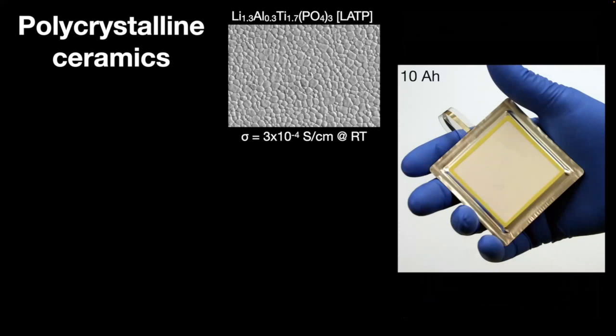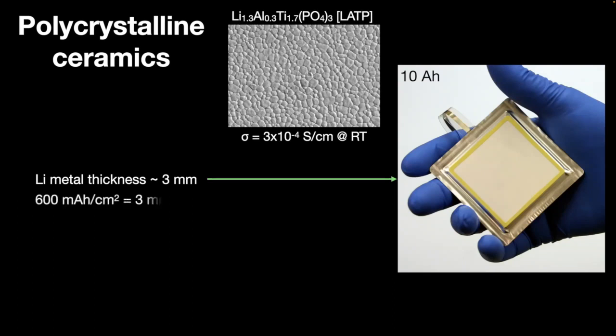Here you see a 10 amp hour electrode. So these are very energy dense electrodes. But behind that ceramic membrane is almost 3 millimeters of lithium. So in other words, it's very thick, very high capacity. And that distinguishes this approach from rechargeables in terms of the cost or the amount of solid electrolyte you need.